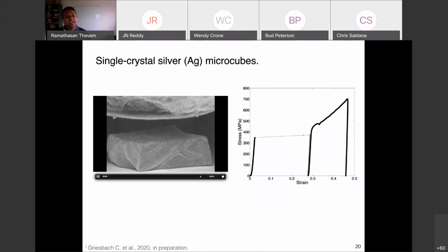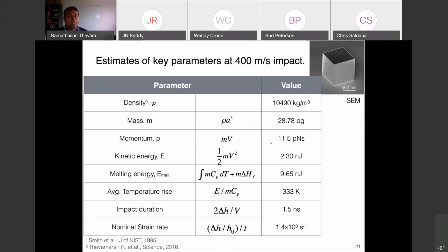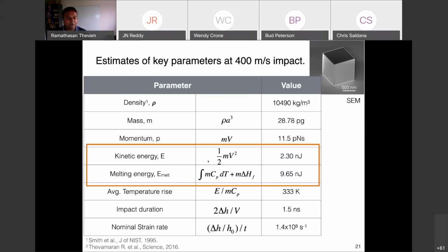What happens is, this doesn't have dislocations initially, so you have to spontaneously nucleate dislocations to cause this massive strain burst in the system. So what would happen if you take these cubes and launch them against a substrate at very high velocities? A velocity of 400 meters per second corresponds to a projectile kinetic energy of approximately 2.3 nanojoules. One thing I want you to pay attention to is that this 2.3 nanojoules is much, much lower than the melting energy of silver.